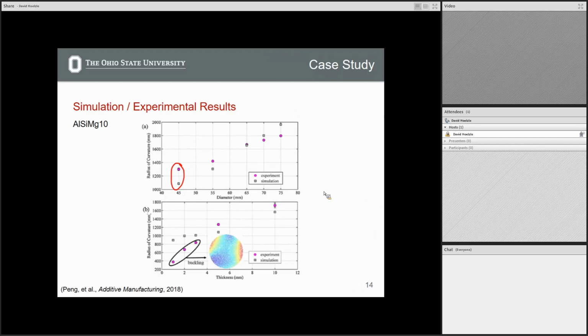And it wasn't bowing up at all, even though, as Brian showed and as we showed, you have a really large residual stress in it. But it now has a really large moment of inertia associated with that, so it's actually not going to distort much.